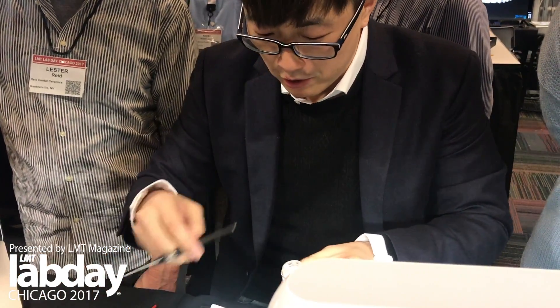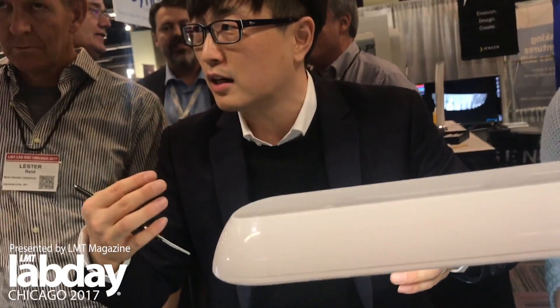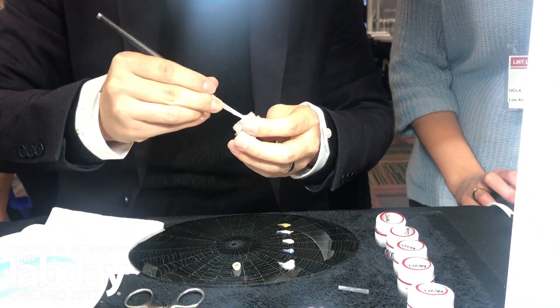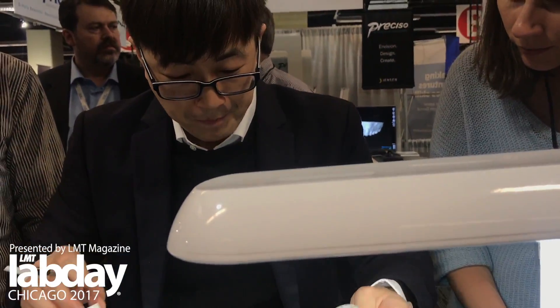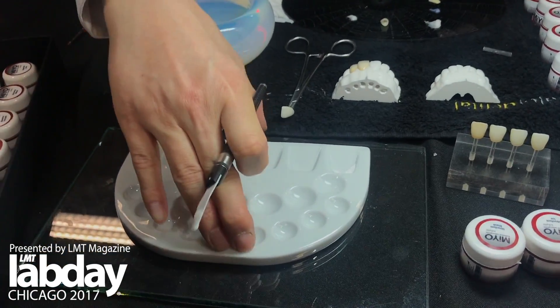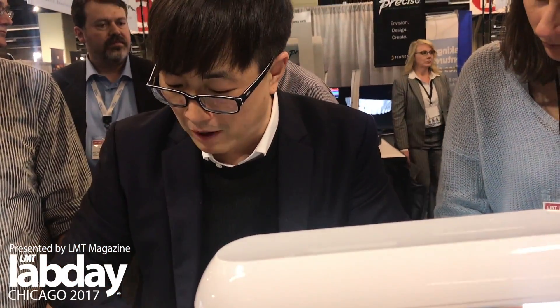I like to polish my zirconia — I don't like to leave it rough. There are a lot of studies showing that when glaze wears off in the occlusal, functional areas, if it's rough it's going to be like sandpaper to your natural teeth. These glaze pastes, you always want to mix them. I had this material on an open palette with a loose plastic lid for about three weeks since I got back from Liechtenstein, and it always felt the same every day.